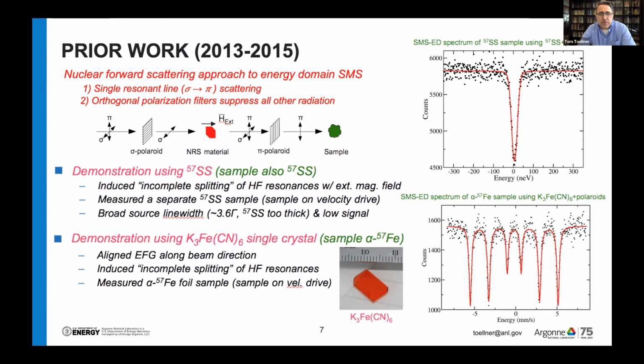The second approach used a combination of magnetic and electric interaction. And here I chose potassium ferricyanide. This is a single crystal. It's a water-soluble salt, so it was something I could easily make in the lab. And it was unenriched crystals, but I picked the principal axis of the electric field gradient, and I made it coaxial with the magnetic field. And I placed that in between the cross-polarization filters, and that allows me to generate a single line.